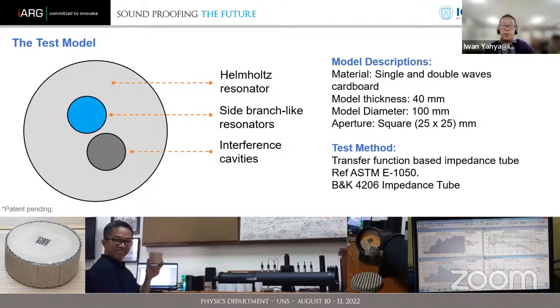This is the data about the material under test. We are working with cardboard, single wave and two wave cardboards. The model thickness is around 40 millimeter. The diameter is 100 millimeter. We are using a big aperture, around 25 millimeter. The test procedure is using a transfer function based impedance tube according to ASTM E-1050, using a Brüel & Kjær 4206 impedance tube.